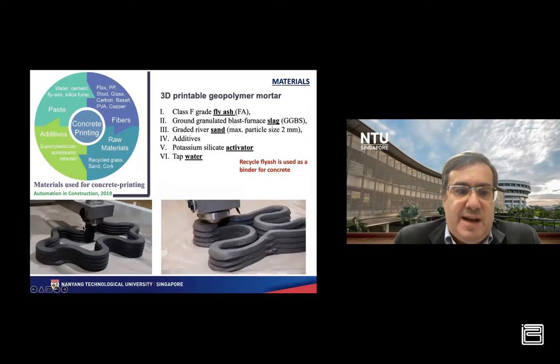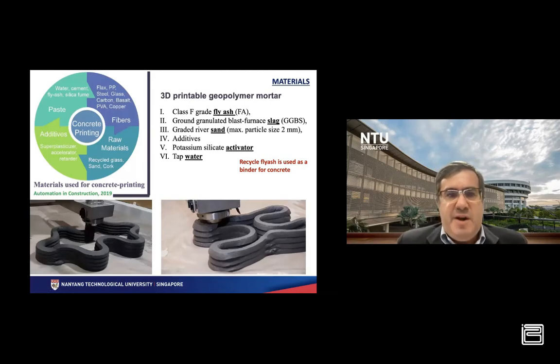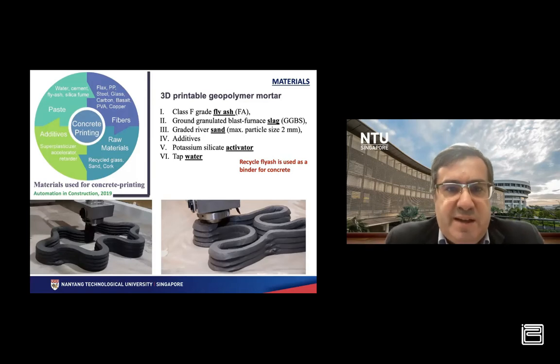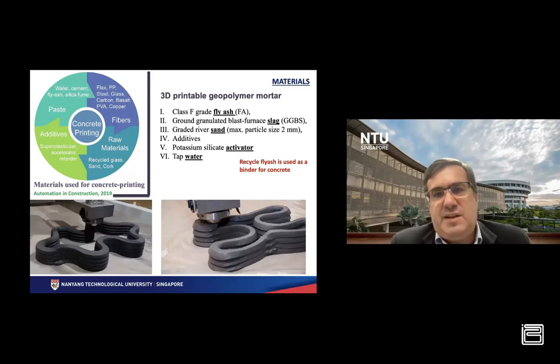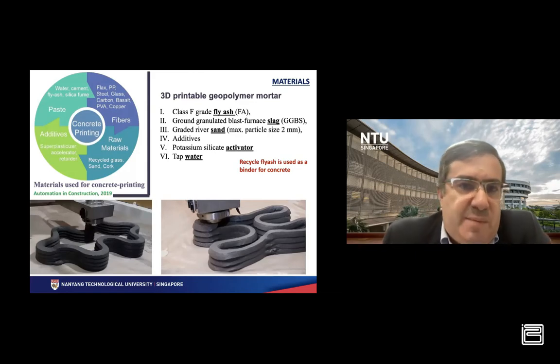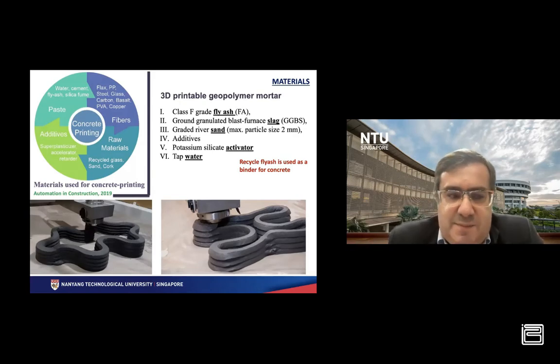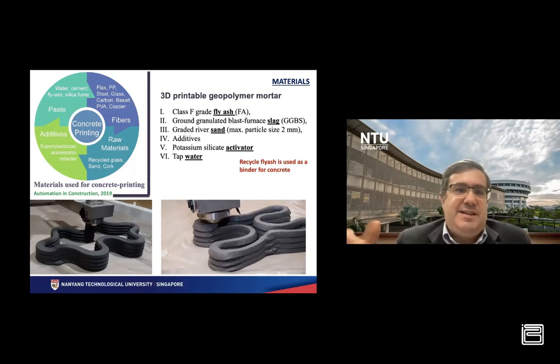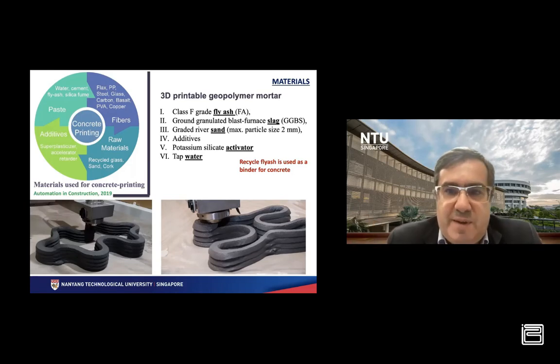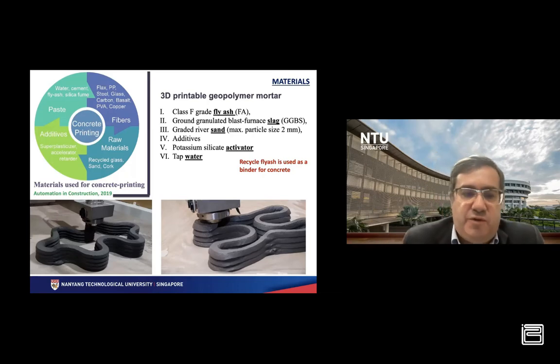Materials represent also an important area, not only for construction, but a very important aspect of our activities in all research pillars. And material certification is, for example, a relevant activity at the center. This image shows the most commonly used materials for concrete printing. In the case of the center, and similar to other research centers, we develop 3D printable geopolymer mortars. We are using potassium silicate activators. So a range of materials, in most cases proprietary materials, materials that we are exploiting with companies for future commercialization.